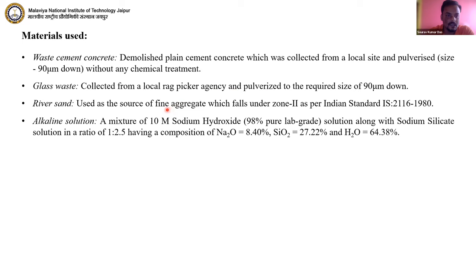Then the fine aggregate used here is river sand of zone 2 grade as per Indian standard. Fourth one is the alkaline solution. We have used 10 molar sodium hydroxide solution with sodium silicate, having an alkali mixture ratio of 1:2.5.